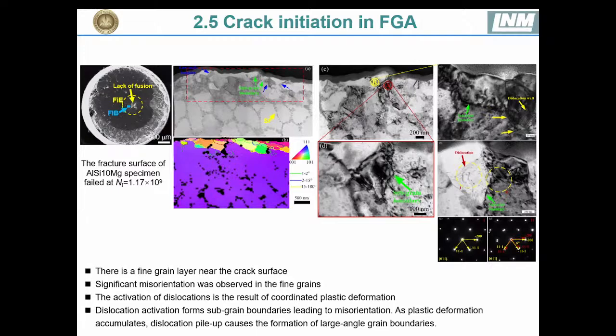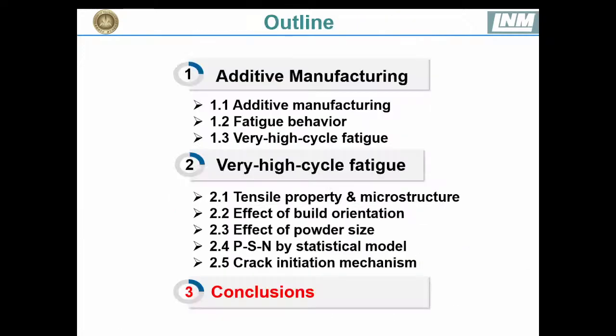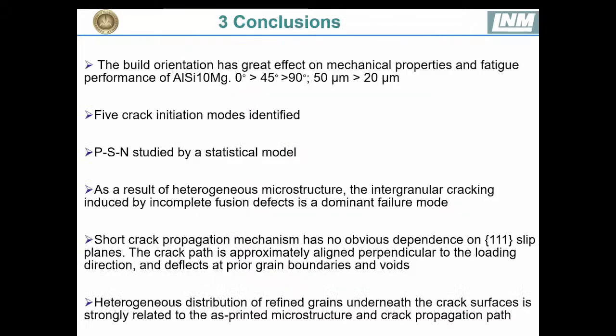result of coordinated plastic deformation, and also dislocation activations from subgrain boundaries will lead to misorientation, and as plastic deformation accumulates, dislocation piles up, causing the formation of large angle grain boundaries. This shows the crack initiation mechanism, as well as the formation of the fine granular area in the very high cycle fatigue. So from what we discussed before, the following